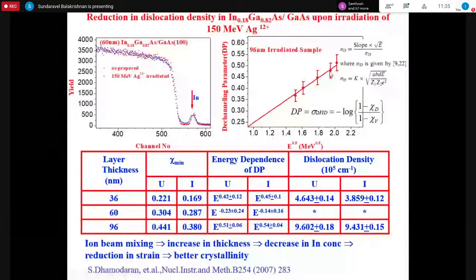Okay, that means that the dechanneling parameter is proportional to E power 0.5, so the defects are dislocations, and from the slope of the curve we can find the dislocation density. Okay, for indium gallium arsenide with different thicknesses, we have done this study for implanted as well as unimplanted samples, and the energy dependence is something like E power 0.42. Okay, it is dislocations, and the dislocation density is something like 4.64 into 10 power 5 per centimeter.